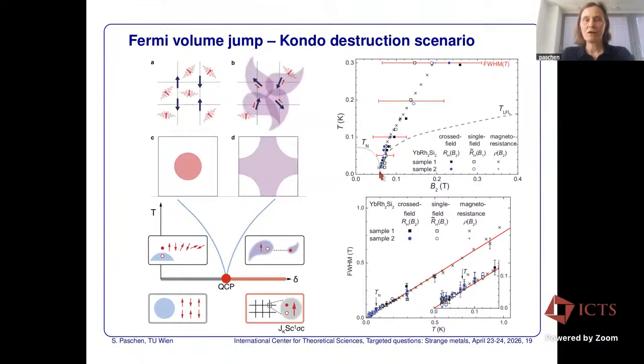The interpretation in the Kondo language is rather obvious. So in a Kondo screened situation, the local moment contributes to the Fermi surface. It's a well-established theoretical statement. But if you break up the static Kondo screening on the other side of the quantum critical point, if you allow for that possibility, then the Fermi surface must jump because the local moments will drop out of the Fermi volume and the Fermi volume will be small. So this Kondo destruction transition is a natural way of visualizing why there should be a Fermi surface change. Then, of course, once you have freed your local moments, they can order. But it's a consequence of the Kondo destruction, and it's not the driver for all the physics.